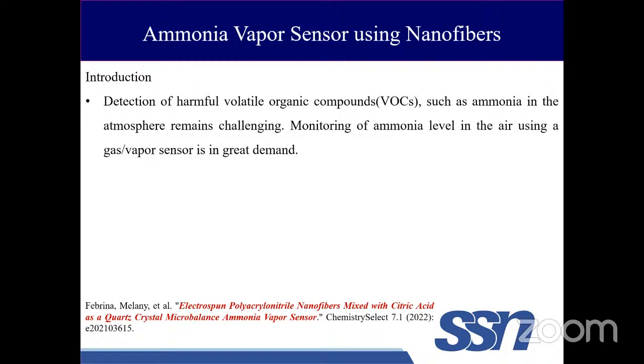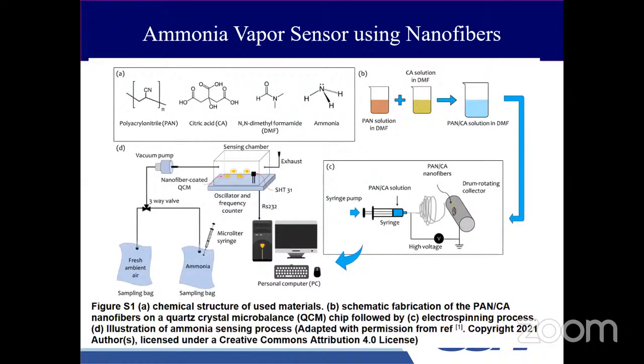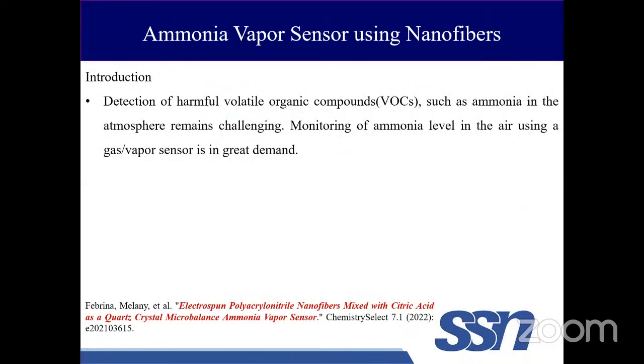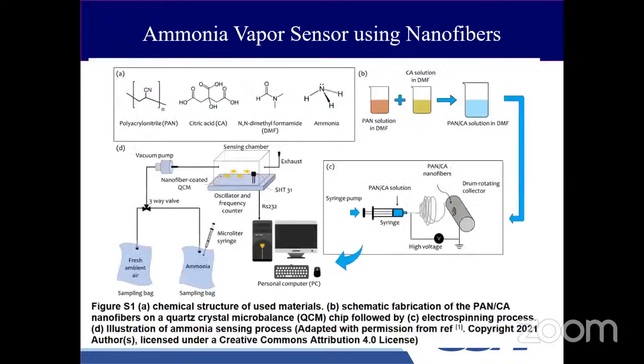Here also they have utilized electrospun nanofibers. What they actually did is they utilized the principle of a piezoelectric material, taking its oscillator frequency. This piezoelectric material is coated with PAN nanofibers that are doped with citric acid. Citric acid has the tendency to interact with ammonia, right? So they have taken a closed container with the piezoelectric material coated with the citric acid doped nanofibers, connected with fresh ambient air and ammonia.